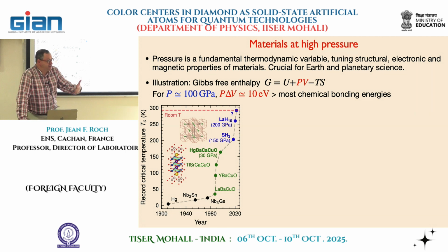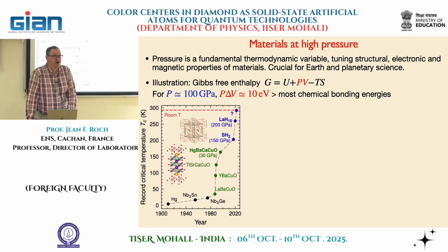Paul Chu also discovered other materials, and especially together with other people, he was able to achieve the highest critical temperature for a long time, which was obtained in a mercury-doped cuprate, and we will work on that. We will show you results that we have done on that. The highest critical temperature, about 165 Kelvin, was obtained at a pressure of 30 gigapascal.